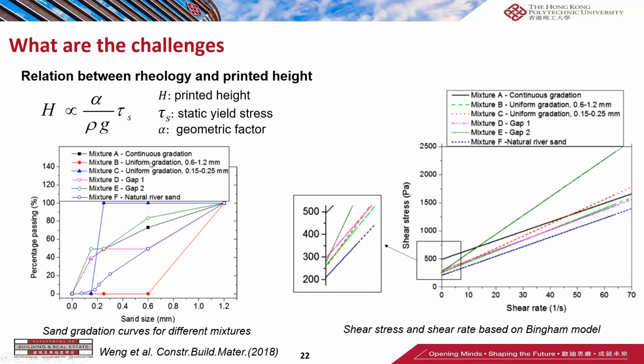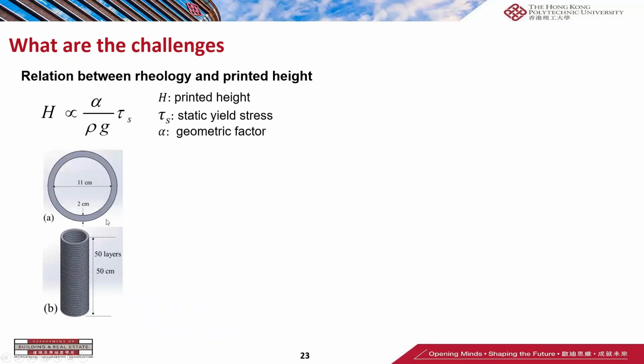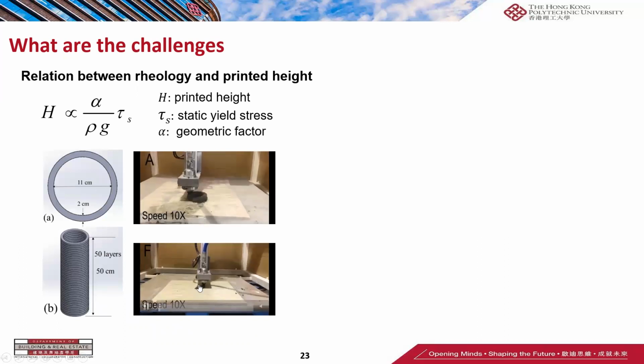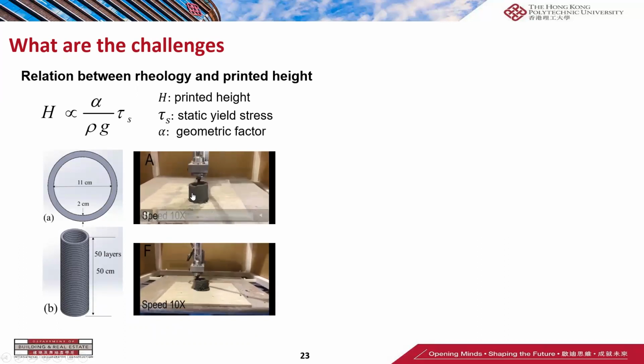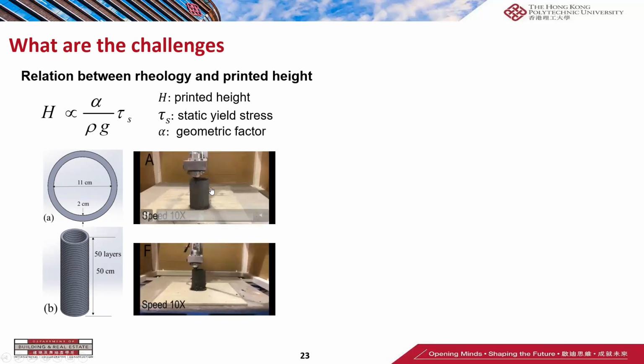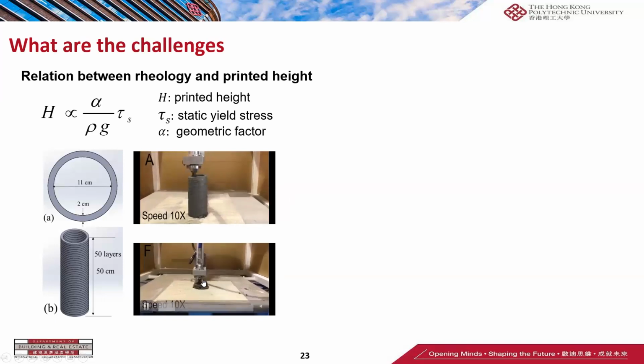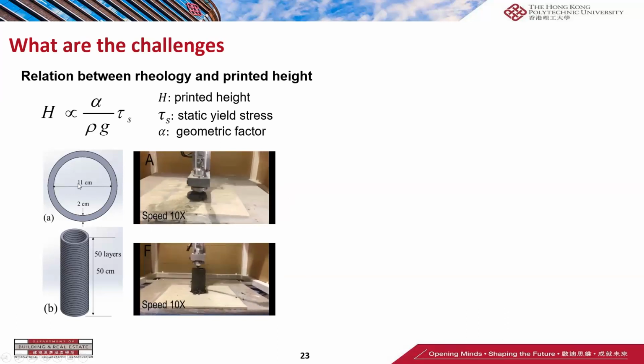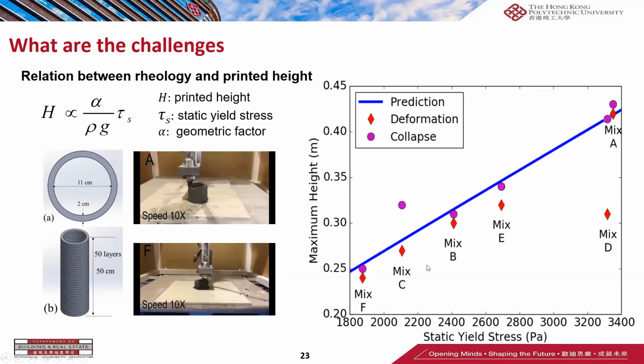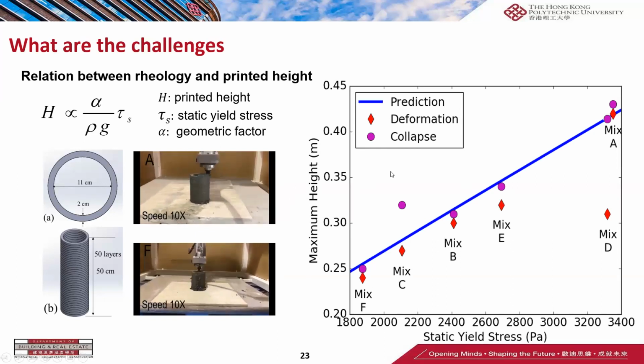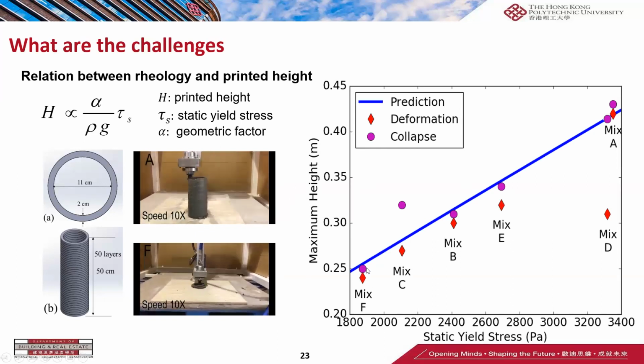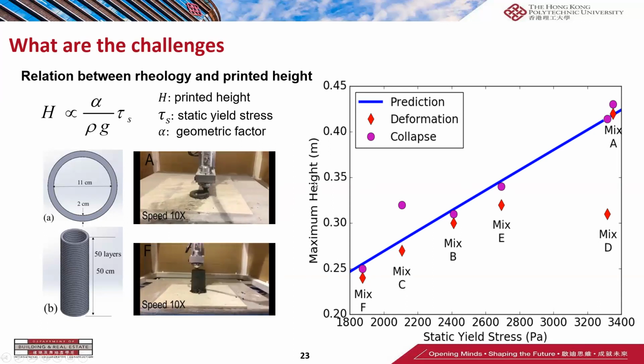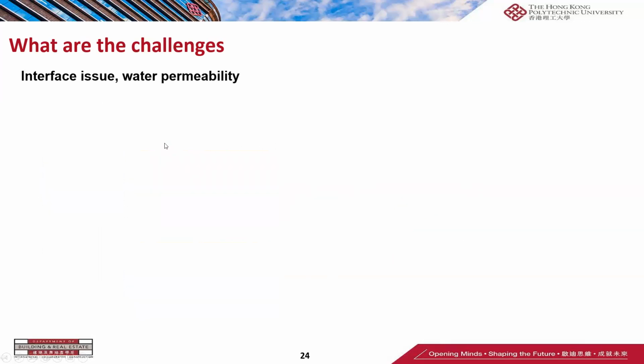Then to further validate this model, we designed this kind of hollow column structure for the printing process. In the printing process, the concrete printer will be adopted to print the whole structure, and then the maximum height will be recorded to indicate the printed height of the materials regarding this kind of structure. Then you can find that this model can give a very good prediction regarding the relationship between the material performance and the maximum printed height. Another challenge in 3D concrete printing is the interface issue.